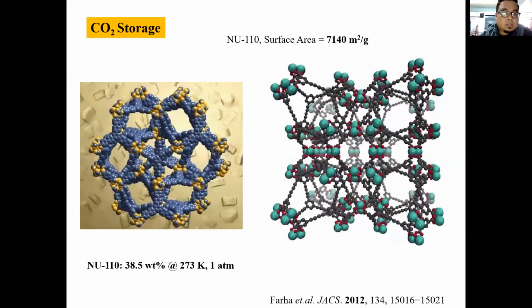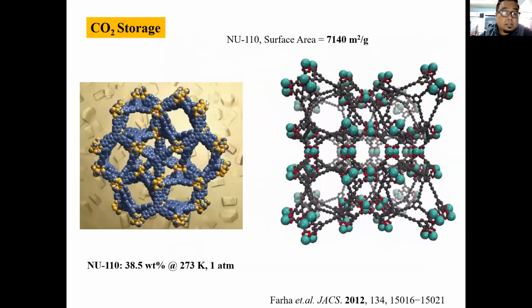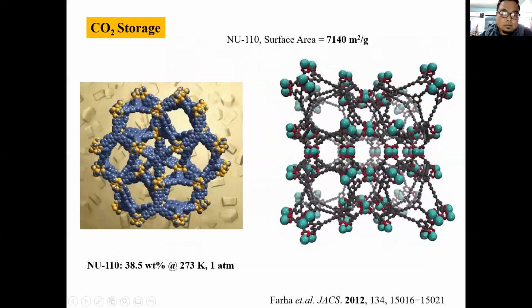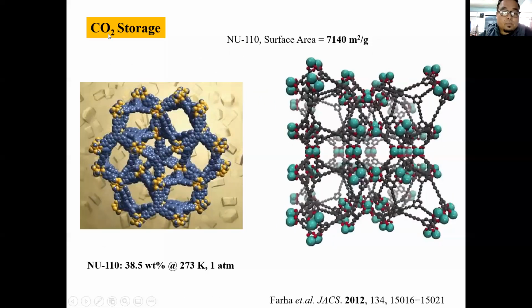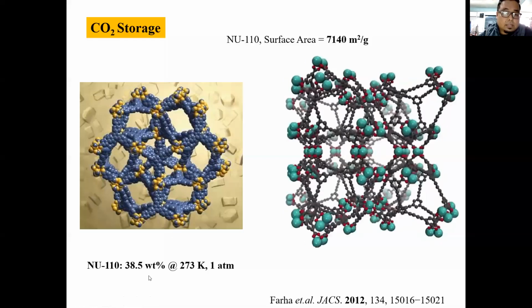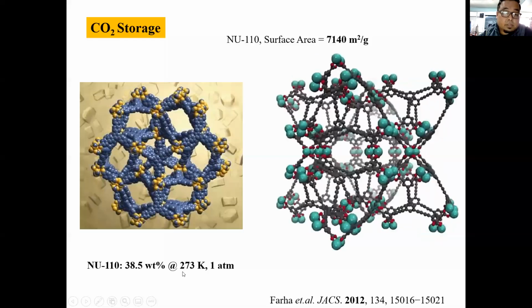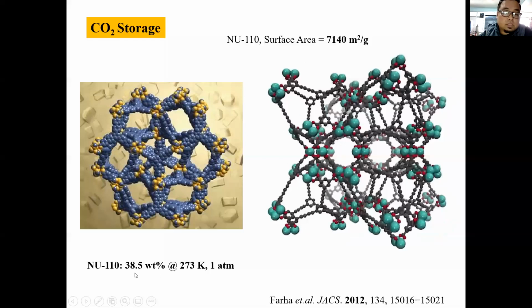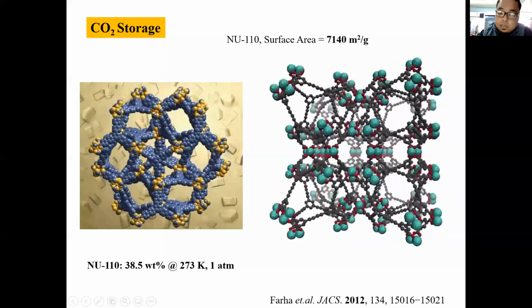For carbon dioxide storage, NU 110 is also highly used. We have this carbon dioxide sequestering process, so we can use these materials. NU 110 actually absorbs around 38.5 weight% at 1 atmosphere. So this is very high. 38.5 weight% is a very high amount. So it can be used for removal of carbon dioxide.